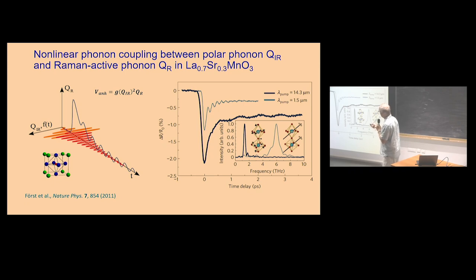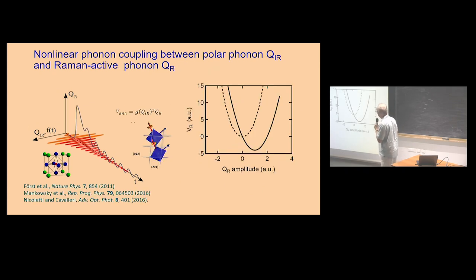So this is quadratic coupling of an infrared mode with another mode, which in this case is a Raman active mode with lower frequency. So there is a high frequency infrared mode coupling with the orthogonal vibration of the Raman mode. This Raman mode can be activated, and it can finally change the crystal structure. And it can be responsible for many other cases. And I will show you here.